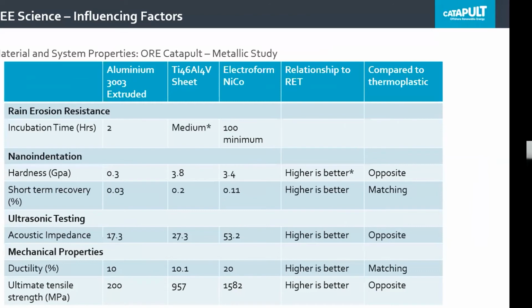ORE Catapult have also done a similar study on metallics. This hasn't actually been published yet, where we've looked at extruded aluminium, titanium 64, and electroformed nickel cobalt. So these are all materials that are used in the aerospace industry. And their rain erosion resistance goes from aluminium at the lowest through titanium to nickel cobalt at the highest.